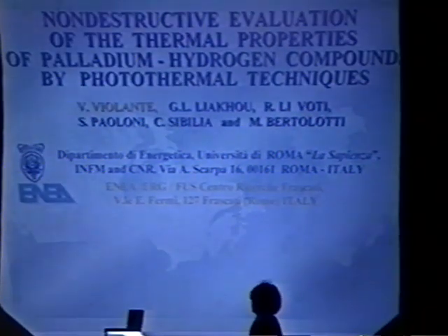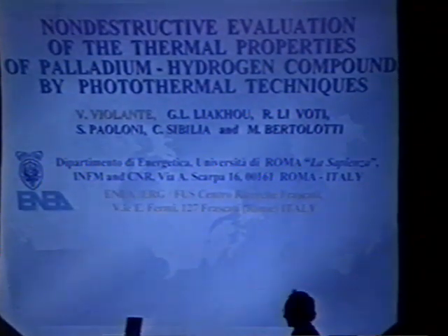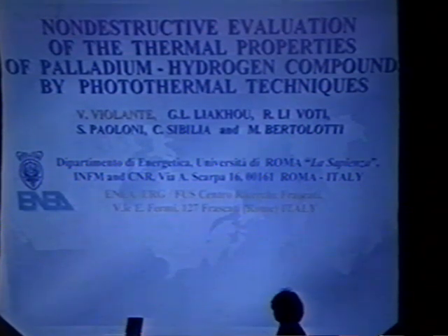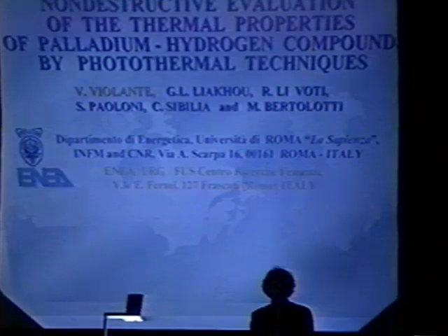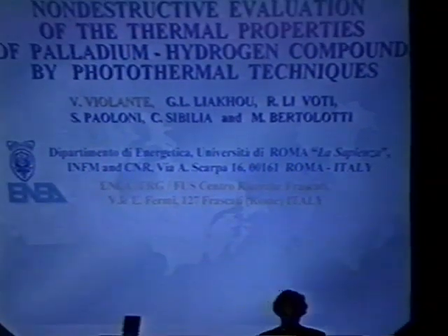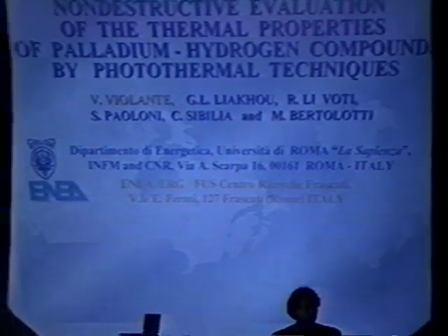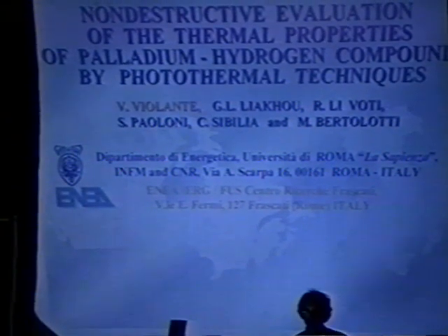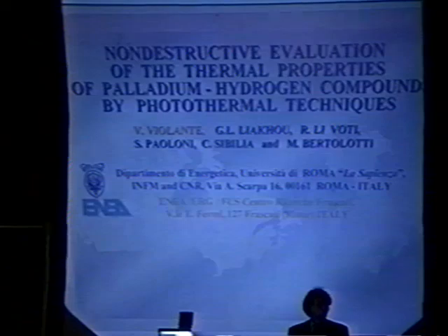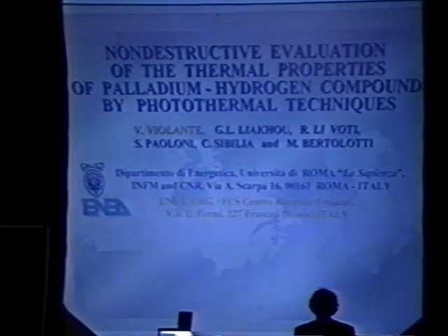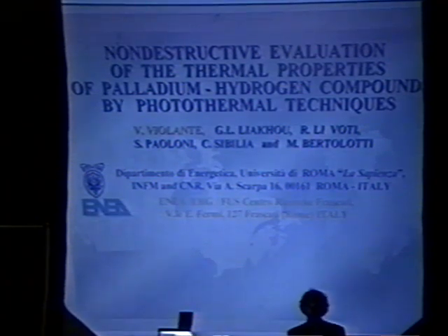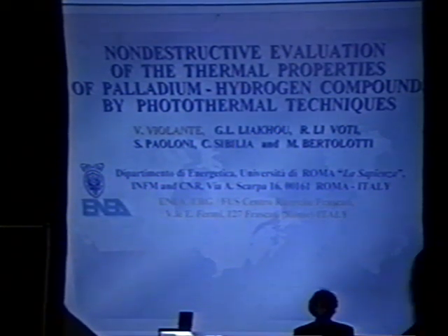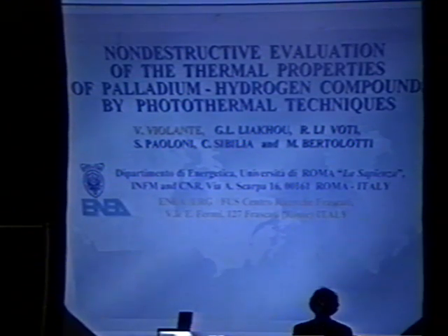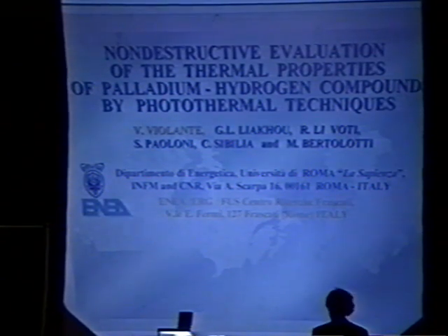This is a material science paper concerning a non-destructive method to evaluate the thermal properties of palladium hydride. The starting point is this one. In our field, we are interested in having a good knowledge of the loading of palladium. But with the measurements we usually do, we can know only an average value of the concentration, and we have to apply some mathematical mechanism to extrapolate the possible profile.